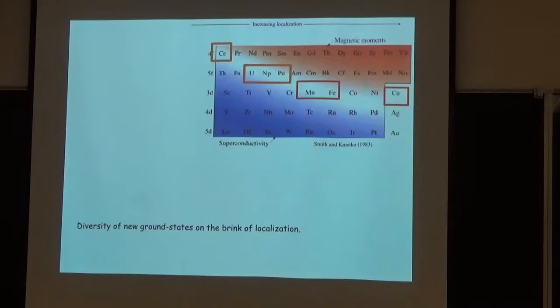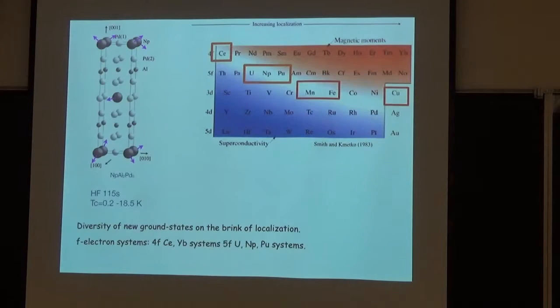And if you take this very literally, then interestingly enough, manganese and iron are at the crossover region. Of course, this is very oversimplified here, but at least it gives us the idea that there may be a diversity of new ground states in the region where magnetism and itinerancy are fighting with one another. One example that we'll come back to is this exotic member of the so-called 115 superconductors, neptunium aluminium 2 palladium 5. This is a fascinating heavy fermion superconductor because it's paramagnetic right down to Tc. It has a Curie susceptibility all the way down to Tc when it goes superconducting, and the local moments vanish as it goes superconducting. We'll come back to that.